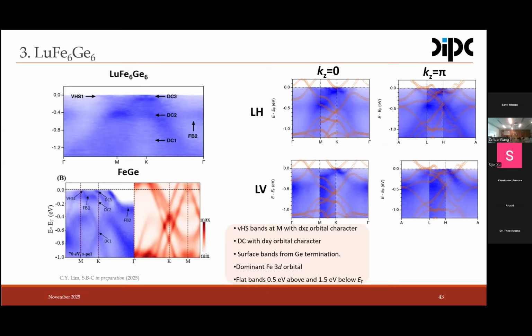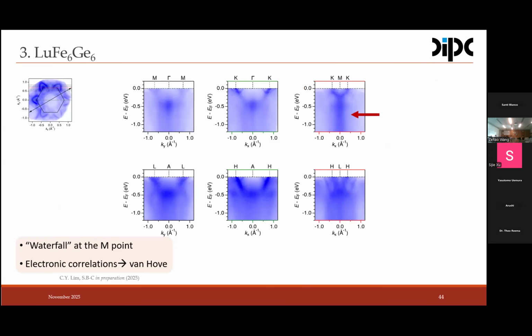And we did the DFT calculations. As of now, we don't have a perfect matching because these are essentially bulk calculations, and we didn't consider the surface terminations. In any case, we are working on this. It is not a high priority now because what I want to show you is that when we do the cut along the KMK direction, which is this cut here, we see at the M point a waterfall of intensity which emanates from the Van Hove singularity.